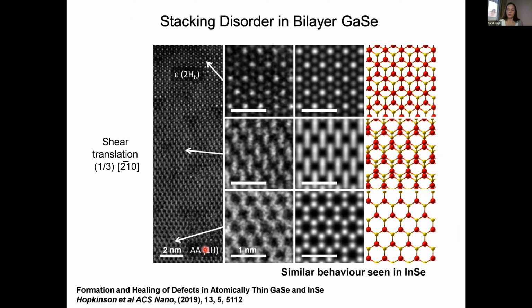We think that's been produced by our mechanical deformation, so during the exfoliation process, but that's really interesting because these types of stacking do not exist in the as synthesized material, and they should have very different optical properties. So understanding that these might be present in your devices is really important, and being able to tune these, which we've shown you can do now by exfoliating along a particular direction, at least we've shown that in graphite, I think is a really interesting area for a future route to tuning the properties of these post-transition metal monochalcogenides.